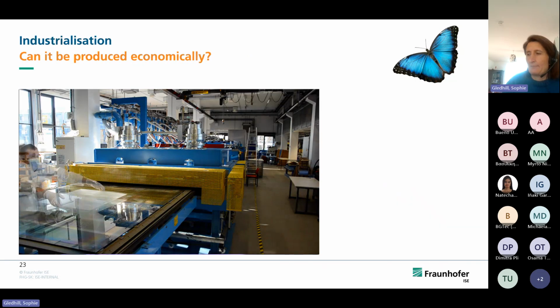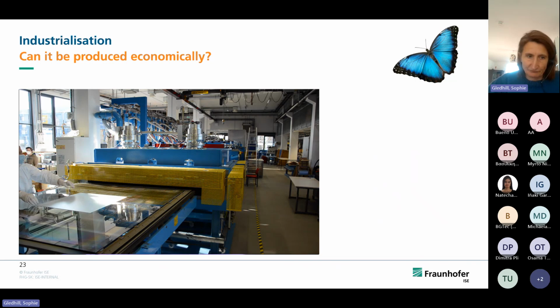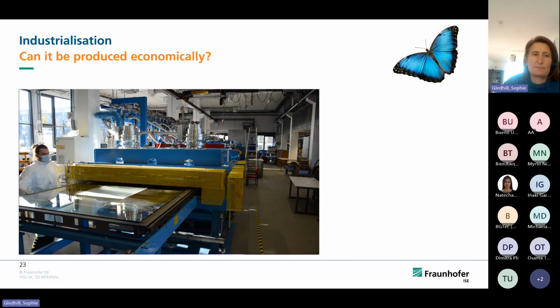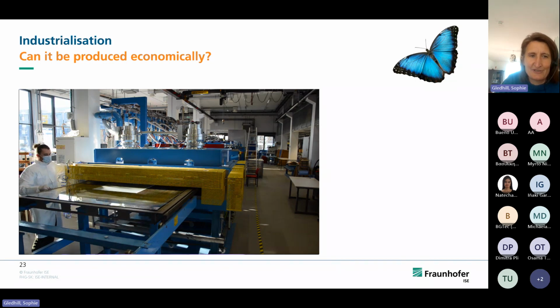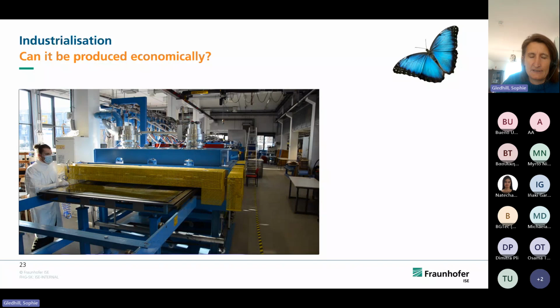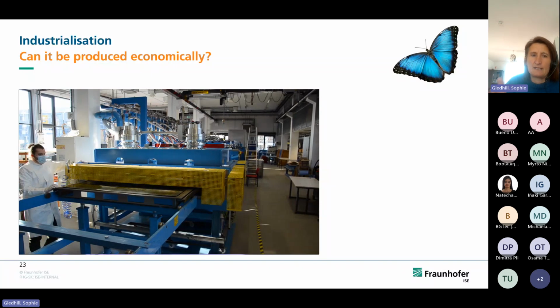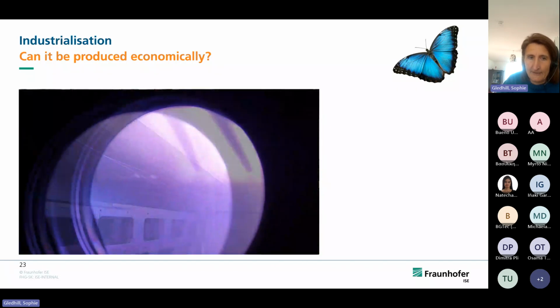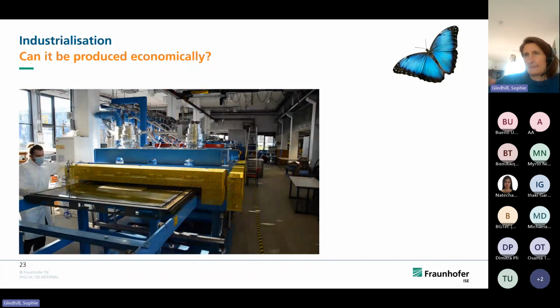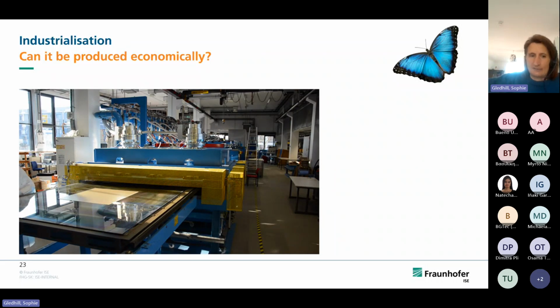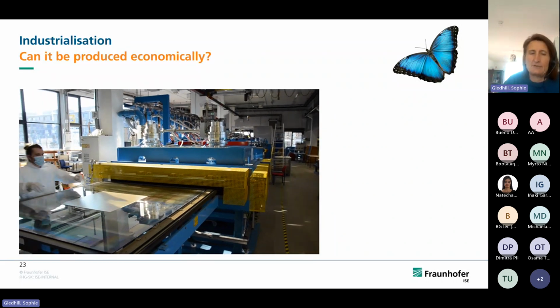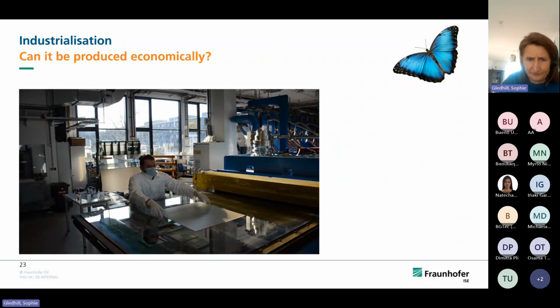So can it be produced economically? As I said before, we're sputtering. The technique is sputtering. You can see Andreas Wessels, our PhD student, loading the sputtering machine. It goes into the load lock, and it's a vacuum system. Once it's through the load lock, it's pumped down to 10 to the minus 6 millibar. We're now seeing our plasma ignited in our sputtering technology, and it goes under the targets, and we get the deposition of our silicon nitride titanium oxide film stack. It then comes out the load lock.